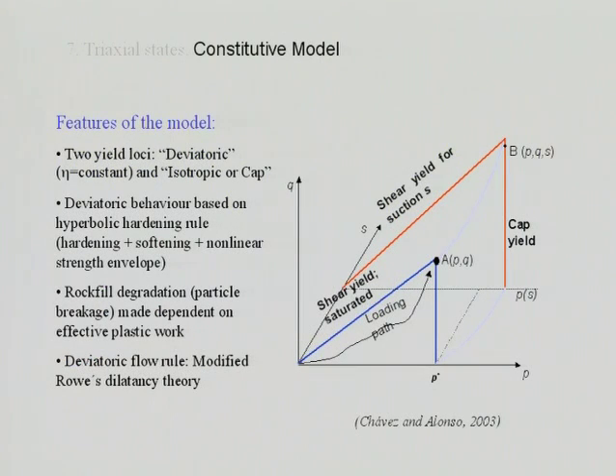At the end, we have proposed a constitutive model for a rock fill that takes into account the effect of relative humidity. Those are the features of the model. One interesting feature, and the only one I'm going to mention here, is that we made the degradation of the rock fill dependent on the effective plastic work. And the effective plastic work was defined as the difference between the total plastic work and the plastic work necessary for rearrangement. The difference probably is associated with particle breakage.